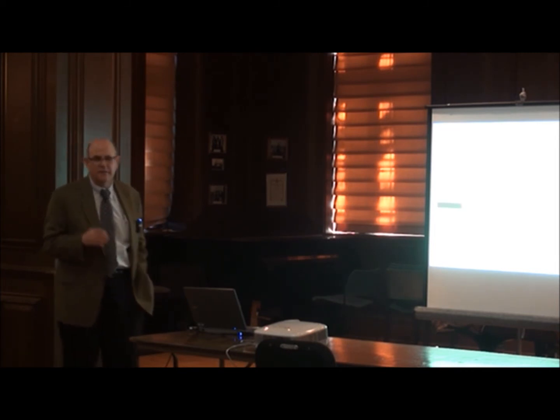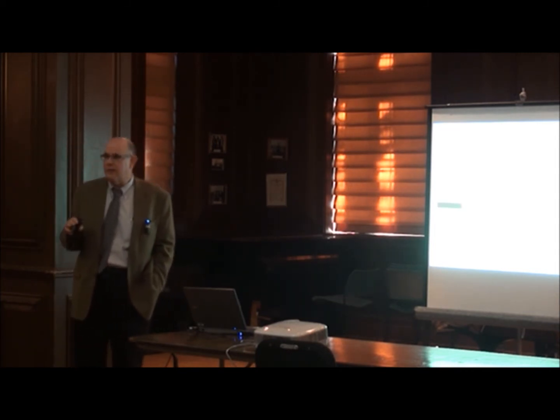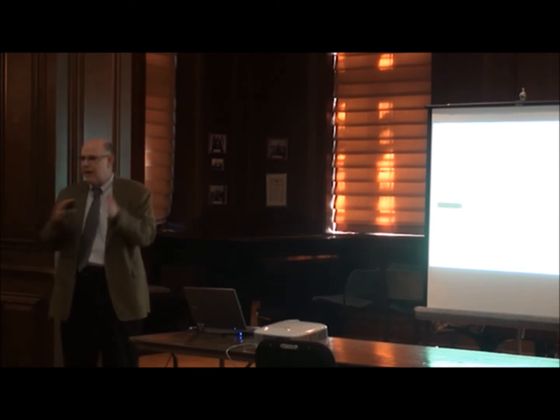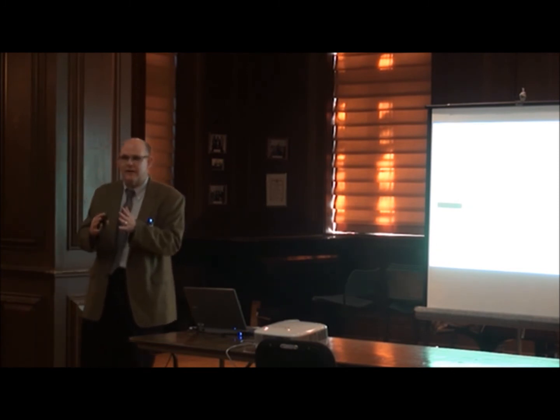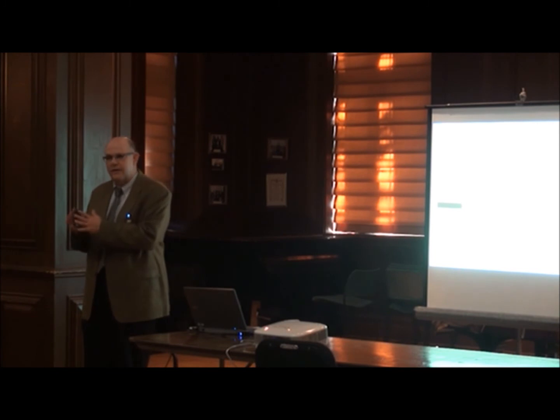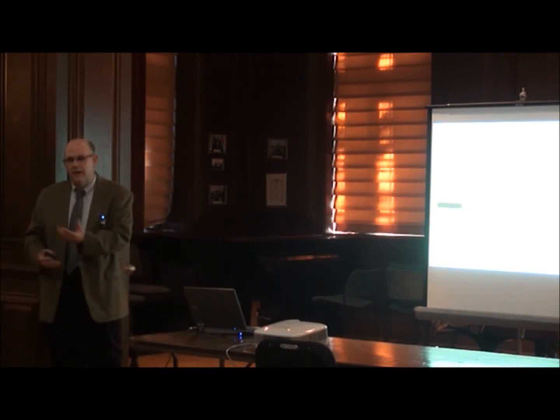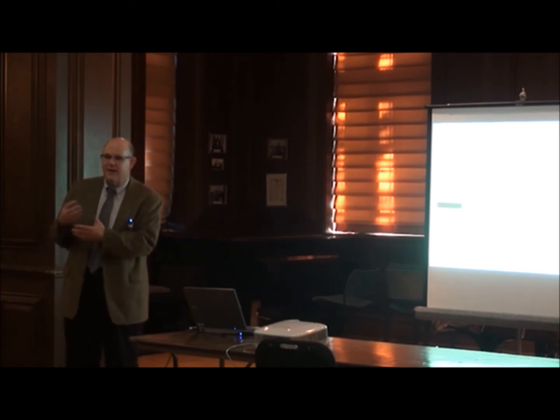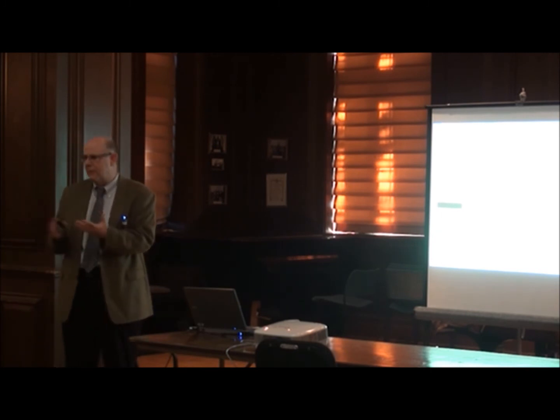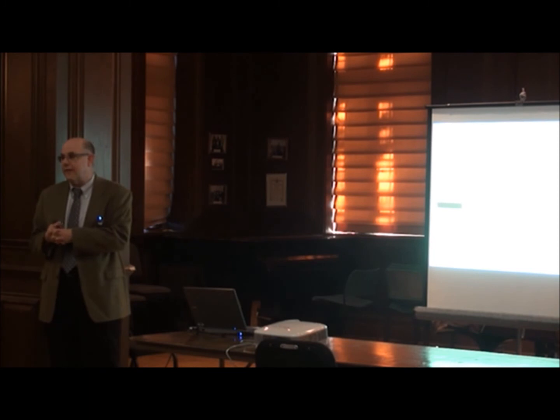What's happened now, which is exciting in this field, is, again, just to summarize here, when it comes to dry sliding friction, it's the real area of contact that counts, and then the asperities that make what the shear strength is of those junctions. When you have fluids involved in a hydrodynamic or quasi-hydrodynamic state, we're worried about fluid flow through the interface and how surface texture affects that.